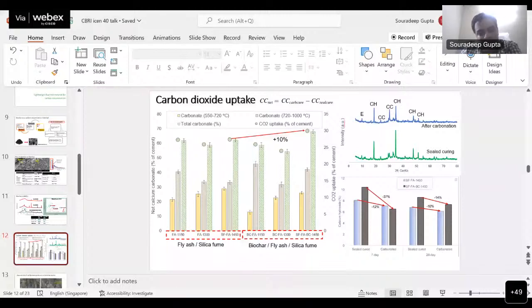Here we have developed materials of different densities, ranging from 1,150 kg per meter cube that you see here to about 1,450 kg per meter cube, containing fly ash and silica fume. This part of the chart shows the mix of similar density but with biochar in it. From this, we see that adding biochar can actually enhance the carbon capturing potential, but that does not take into account the carbon present in the biochar. If we add that, it can enhance it further by about another 5 to 7%. This carbon capturing potential was investigated using XRD and thermogravimetric analysis.